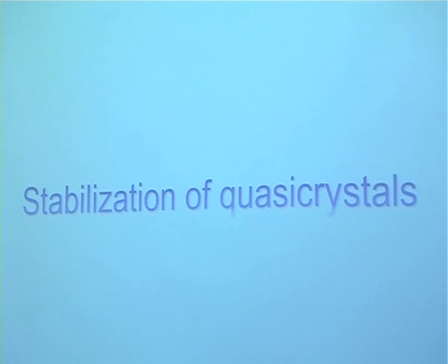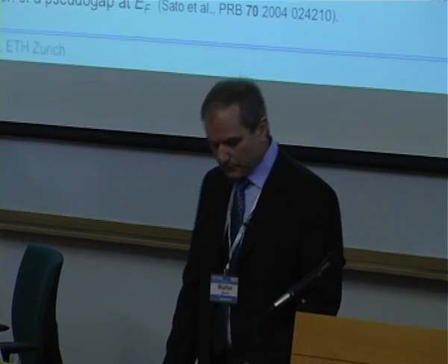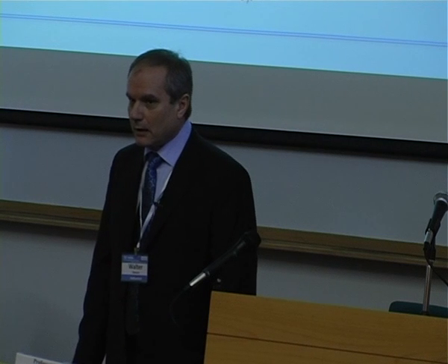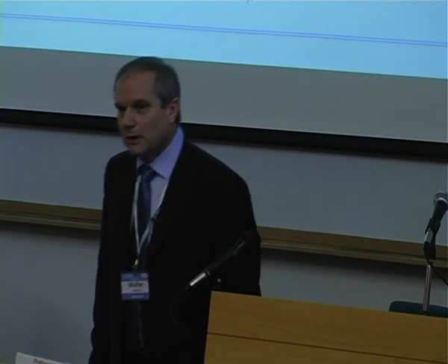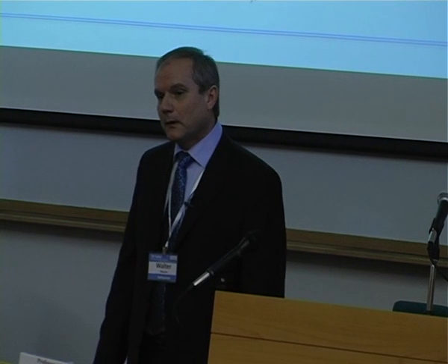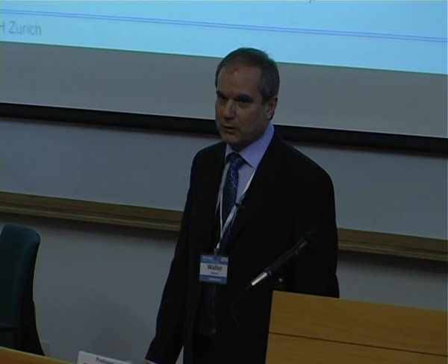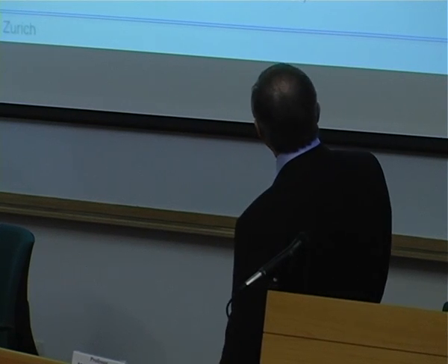Stabilization of quasicrystals. That's a difficult question because there are so many alternative structures which could also be formed instead of quasicrystals. But for intermetallic phases, basically electron concentration plays an important role. And this is on one hand the Hume-Rothery mechanism, so that you get a pseudo gap at the Fermi energy, or it's a kind of hybridization inside of clusters which stabilizes the quasicrystal.